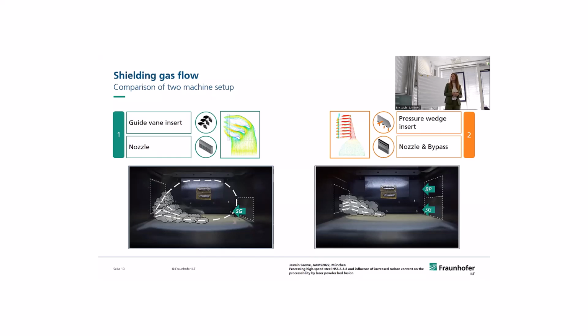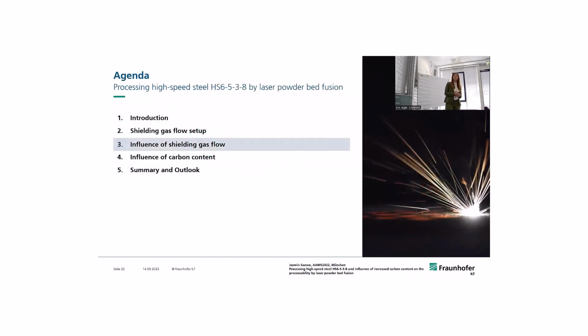And we used those two setups to investigate the HS6-5-3-8. And how did we do it? We have an experimental setup. Our material needs to have preheating. So in previous process parameter studies, we found that using preheating of 350 degrees enables crack-free processing of this very high carbon content steel. So we were very happy that we are able to process it crack-free.